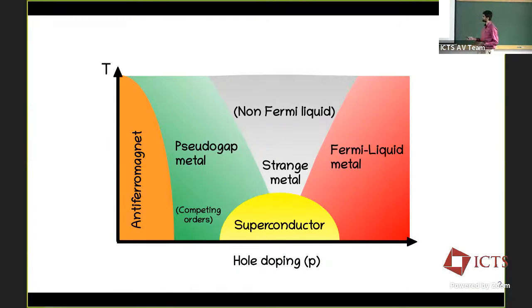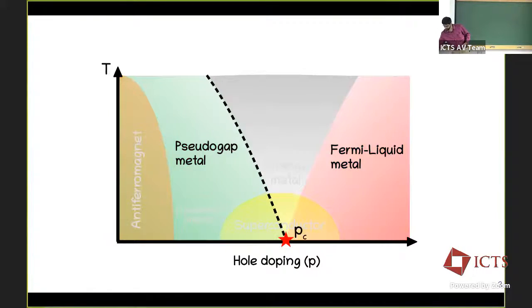Just to get everyone on the same page, continuing from yesterday's discussion, I showed you this phase diagram for the cuprate physics, which is a complicated high Tc superconducting material with lots of phases. But in the end, we saw that recent evidence and observations suggest that there are some fundamental questions that you can ask. Could we have a quantum phase transition as a function of doping between some metallic phase at low doping with some spin glass order, presumably, and some Fermi-Liquid-like phase at high doping? We looked at this quantum critical point using renormalization group theory, considering a particular random model, this random t-J model, where we started with an SYK model, which was a Mott insulator with random exchange, and then we doped it.